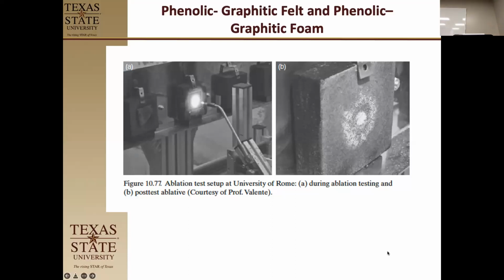Okay, so the first ring here is where you have the highest velocity of gases and the highest heat. So that's where you're going to get the worst of it. The outer ring here, this is a lower heat flux, and you have gases actually streaming horizontally. So here, they're hitting down, then bouncing up and going horizontal. So this zone here has a different heat flux and a different gas flow. It's not skipping over, as the gases are shooting up this way, there's still depositing heat there. Most of the heat was deposited by the time you get out to the outer ring. This area is still heated up, right? But it didn't heat up enough to decompose the matrix. So just as here is where you're actually doing a lot of ablation, here you're just decomposing the matrix.